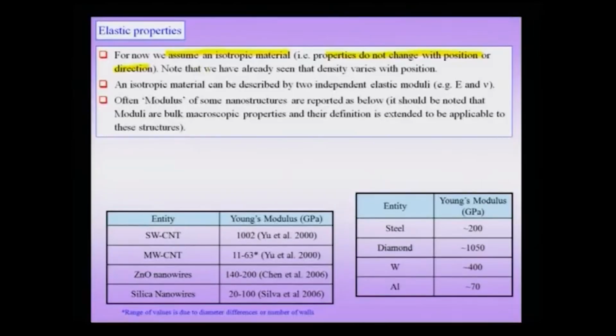And this assumption is drastic, as we shall see for now, because we already noted that if you take a polycrystal, a nano polycrystal, actually the density and therefore, the modulus will vary from position to position. As you get close to the grain boundary, you expect a different modulus as compared to that in the bulk of the grain.